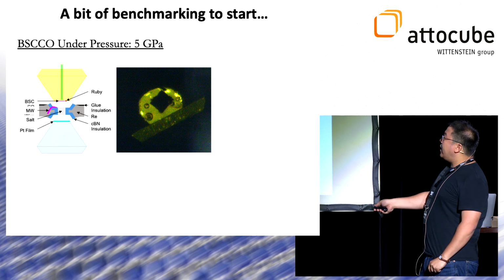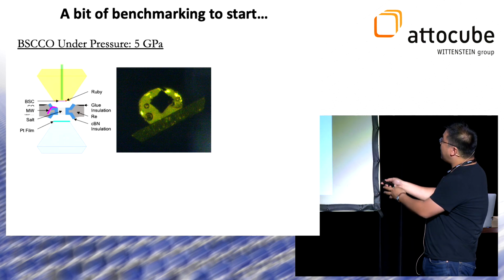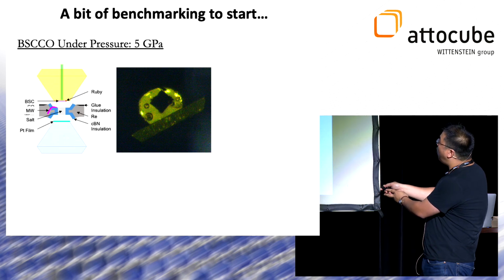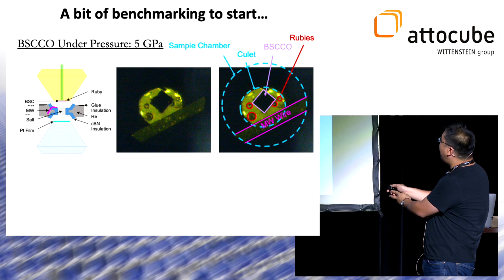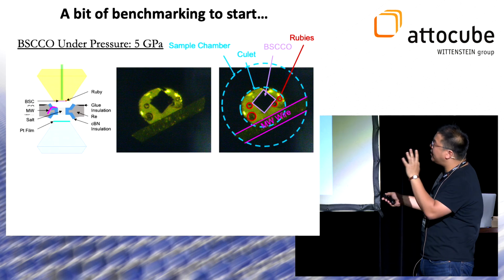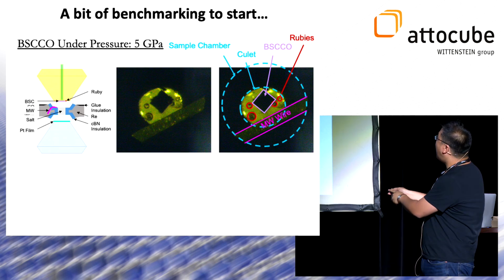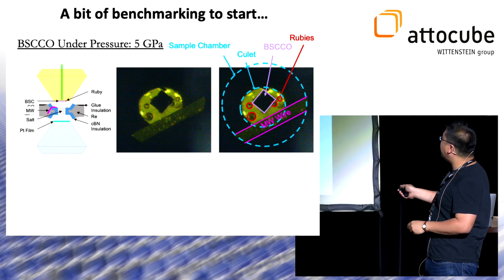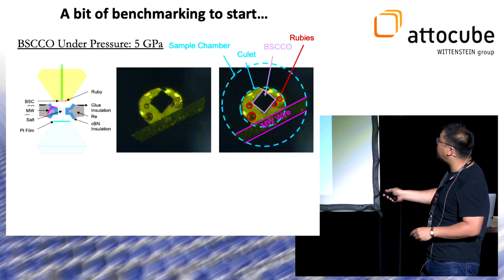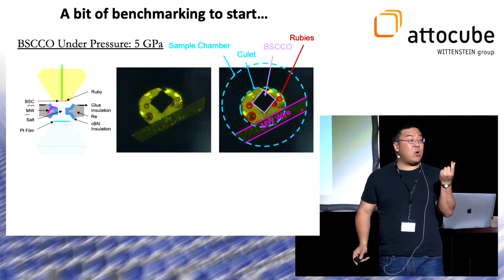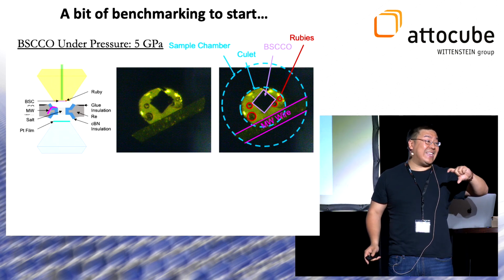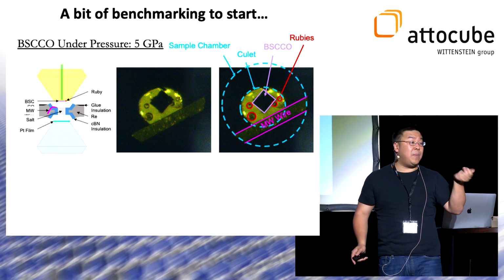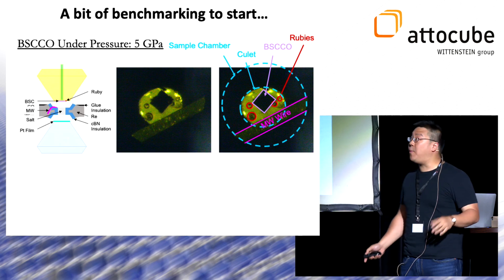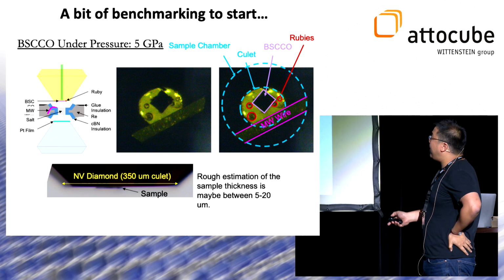The geometry of the setup is extremely simple. This is a white light optical image of the sample chamber, and you can see that the sample of BSCCO is about 50 microns or so. There are a couple of pieces of ruby here, as I mentioned, that we use to calibrate, and there's a microwave wire that you can see obstructing the optical view. That microwave wire is important because we're going to be doing magnetic resonance spectroscopy, so we need microwaves to be able to change the population. That's the basic geometry.